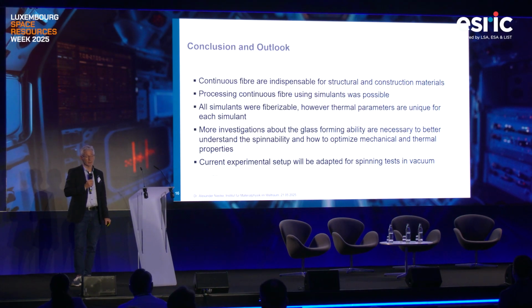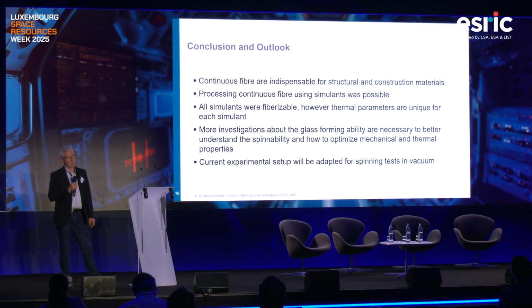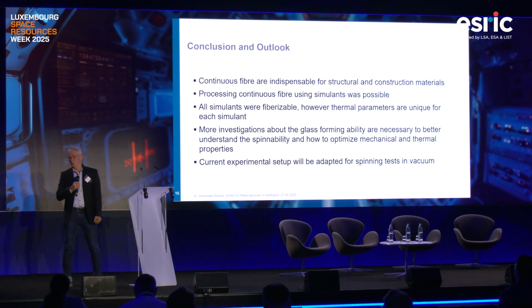So the conclusions are that continuous fibers are indispensable for structural and construction materials. Processing continuous fibers using simulants was possible. All simulants were fiberizable, however thermal parameters are unique for each simulant. More investigations of the glass forming ability are necessary to better understand the spinability and how to optimize the mechanical properties. The current experimental setup will be adapted for spinning in vacuum and therefore lowering the spinning temperatures. Thank you very much.